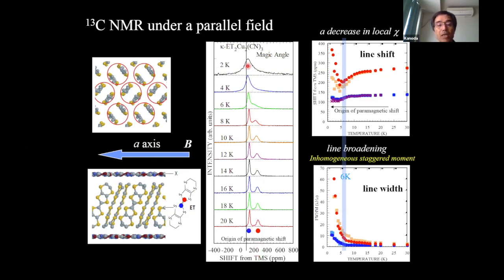This black line indicates the origin of the Knight shift. Namely, the position of the black line corresponds to zero Knight shift. So all of the lines approach this origin of the Knight shift. This means that the local field decreases steeply at low temperatures. And at the same time, line broadening occurs. So the properties are summarized by two features. One is the steep decrease of the average local field. And at the same time, the very steep broadening of the NMR line widths. So inhomogeneity occurs below 6 Kelvin. And this is an experiment under 8 Tesla.